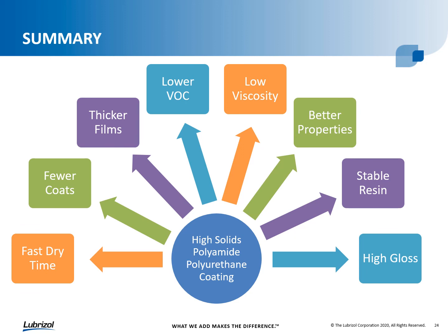And again, we're able to overcome some of those challenges of sometimes pushing the resin solids higher and higher, such as package stability and viscosity. We see here with the high solids polyamide polyurethane that while coming in around 50% solids, we're able to supply that material at a very standard or low viscosity. It is very stable, both the resin and the formulated coating, both at ambient conditions and when accelerated heat age stability testing was done. And from being based on this polyamide polyol chemistry, we see better properties, as we saw in the presentation, delivering very solid performance.